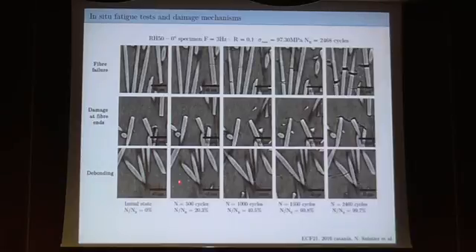Third type is debonding. You don't see it very clearly here, but you have debonding occurring here on the fibers. It's quite hard to distinguish because you have phase contrast here, but clearly we observe that parameter. I will show you maybe more clearly next time, but maybe you can see it here quite clearly. Debonding here, and you have small cavitations here that appear.